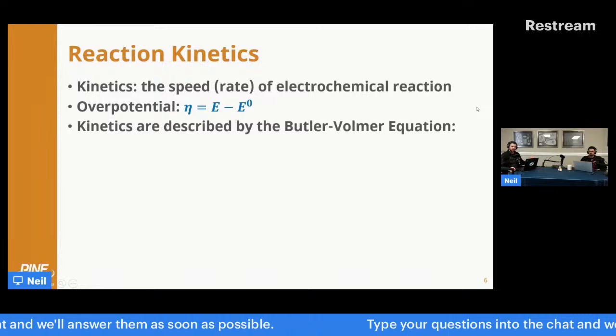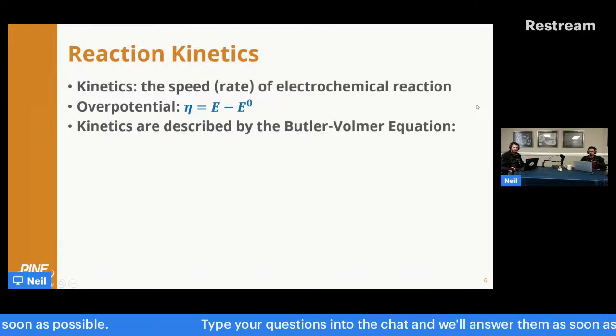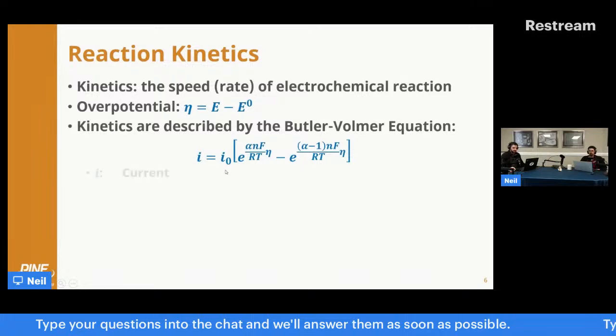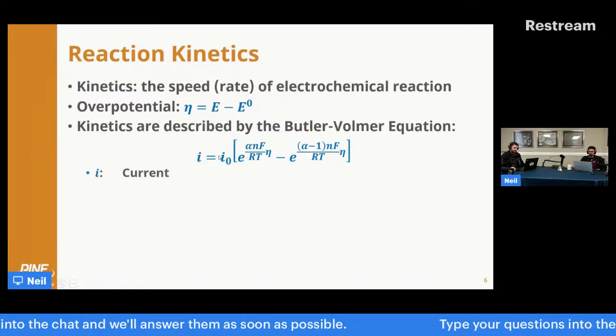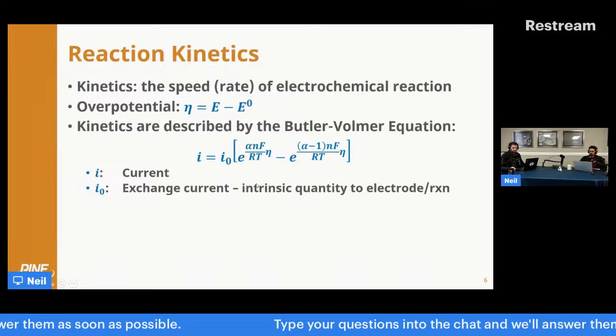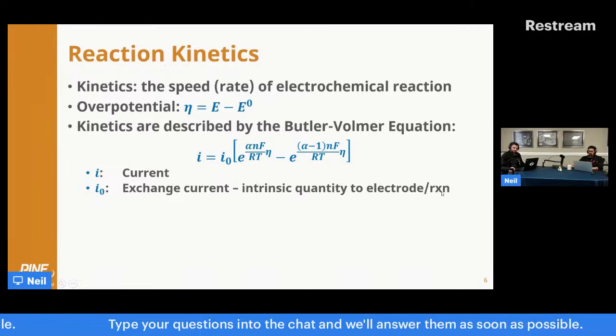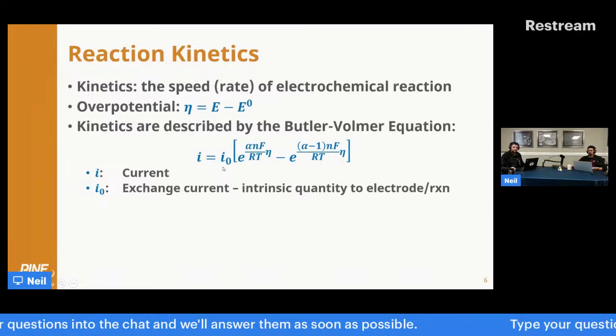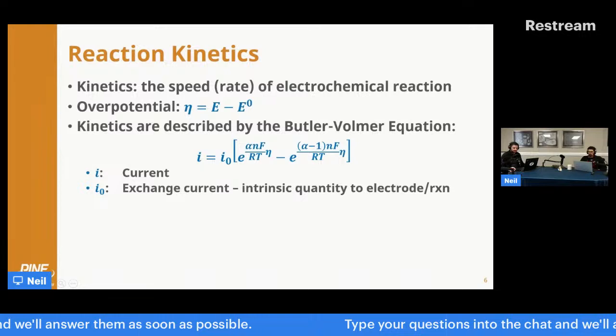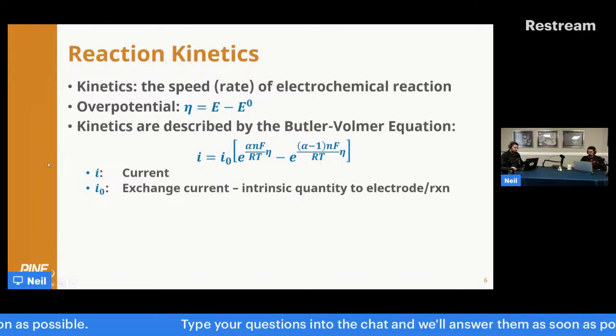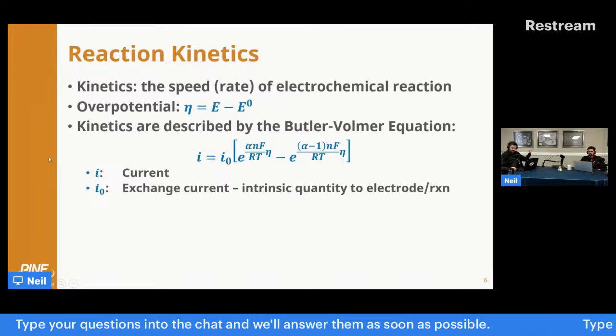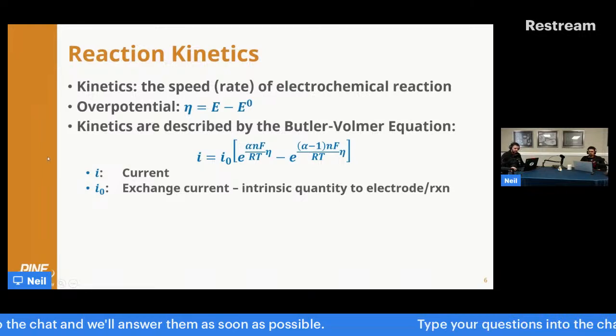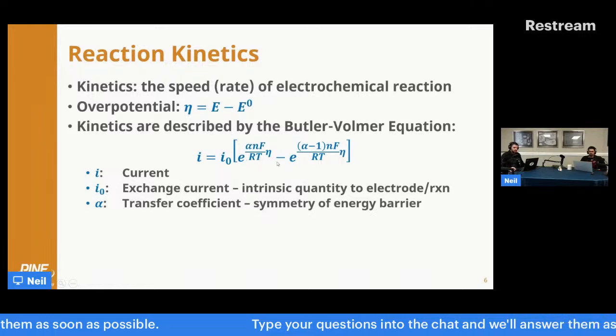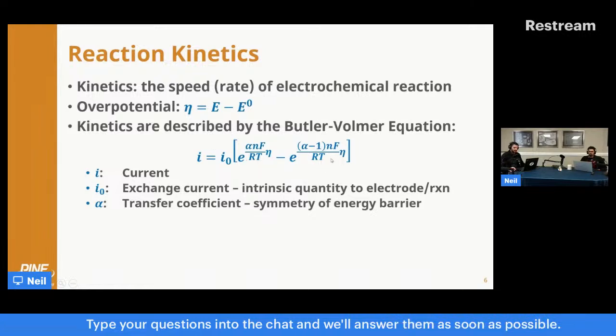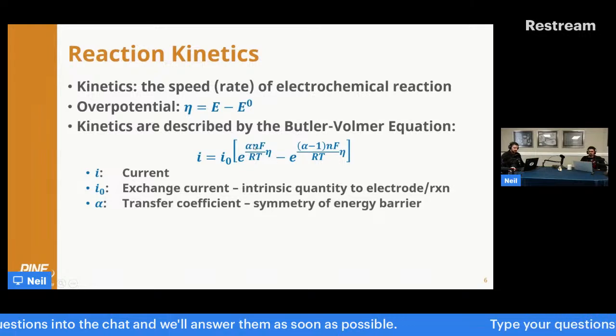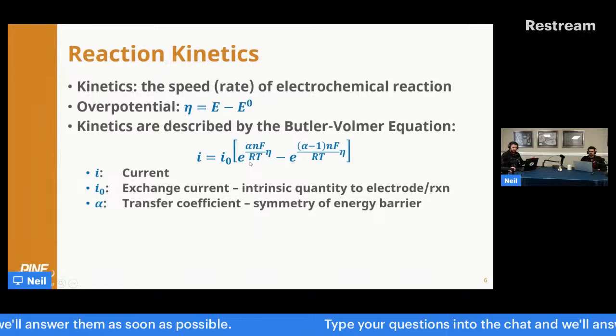the fundamental electrochemical equation used to define kinetics, and it looks like this. Effectively we have current as a function of the exchange current, which is an intrinsic quantity related to the electrode and the reaction. It's really an extrapolation of the heterogeneous rate constant. This is all kinetics. It's just like a kinetic constant of your system, and then you have this exponential formula in brackets, which includes a transfer coefficient, which is basically a measure of the symmetry.